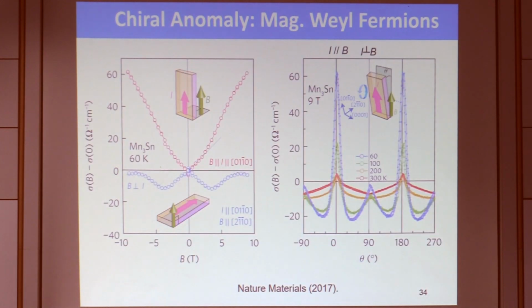So we tested this using this manganese-tin material and found that this is exactly the case again. When we apply the magnetic field along the electric field, there is positive magnetoconductance, and when they are perpendicular, it is negative. And when you rotate the magnetic field from the parallel direction, it drops quite dramatically. This is something you don't see even in a ferromagnet, I think, and this has never been seen in magnetic materials. This is quite a dramatic change, and it is fully consistent with what is expected for chiral anomaly.